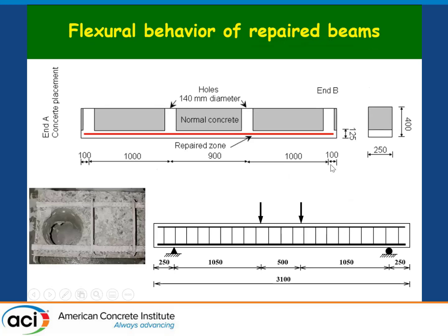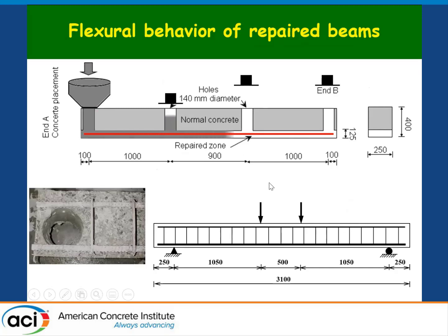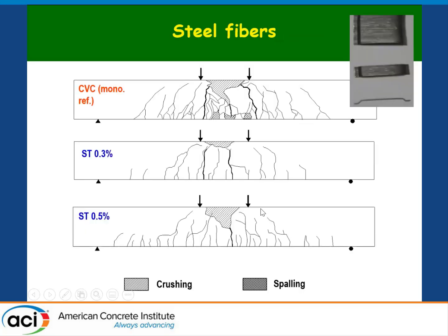In repair applications, we're interested in repairing piers or repairing beams or girders where there's some corrosion and the concrete is removed. And then the beam is basically repaired from the top surface, and the tension zone over here is filled with SCC. And in this case, we'd like it to be a fiber reinforced SCC to reduce cracking and restrain shrinkage and improve flexural performance. And we've done a lot of work on this, and I'm not showing this, but this is just an example of one of the fibers. And this is the conventional concrete, monolithic versus the ones with fibers.